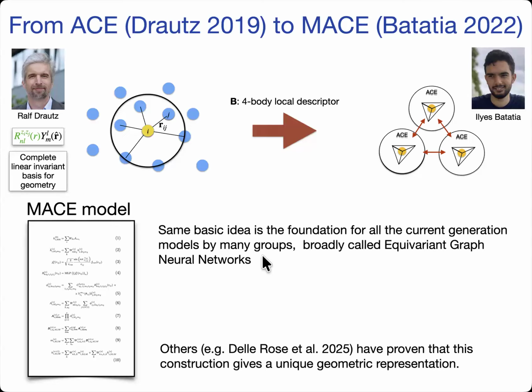But there's a lot of deep geometry here. So, for example, in this paper, Delle Rose and colleagues in 2025 have proven that this construction of four-body local representations passed around once and re-expanded gives you a description of the geometry which is unique. So you can reconstruct each atomic environment. To my knowledge, this is the only proof that there's one kind of descriptor for which it is proven that you can reconstruct. ACE is a complete basis if you don't truncate it. So if you go to arbitrary body order, then of course it's complete, but no truncated version actually is proven to be enough to reconstruct the local geometry.